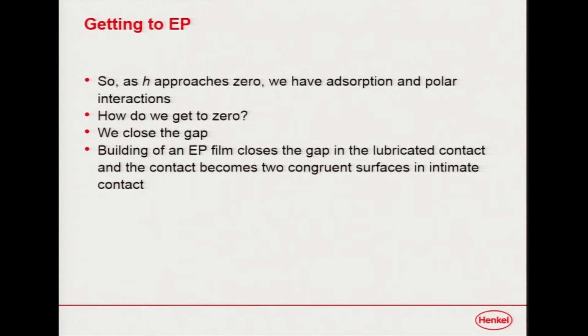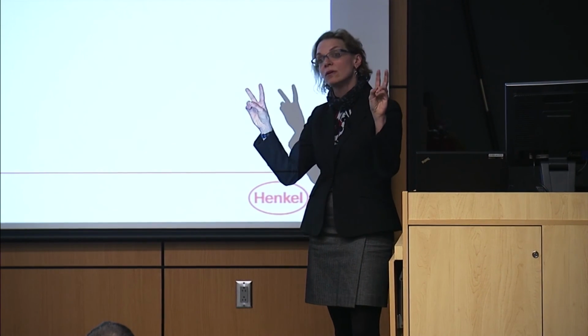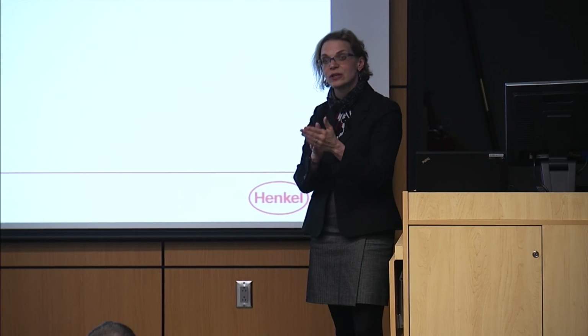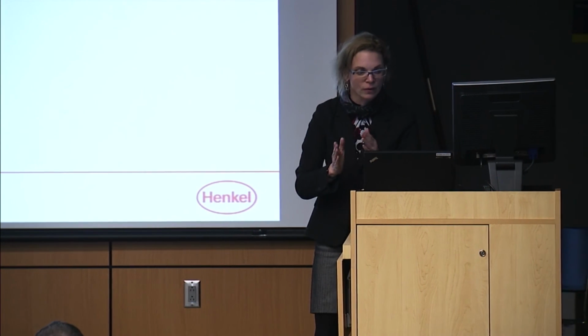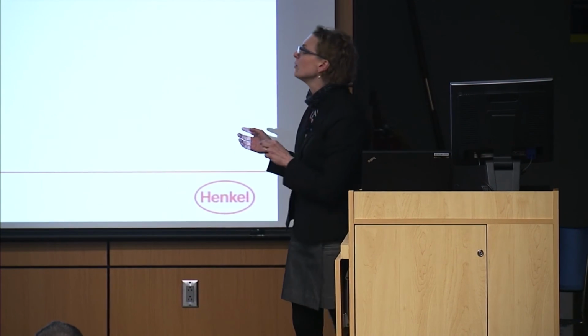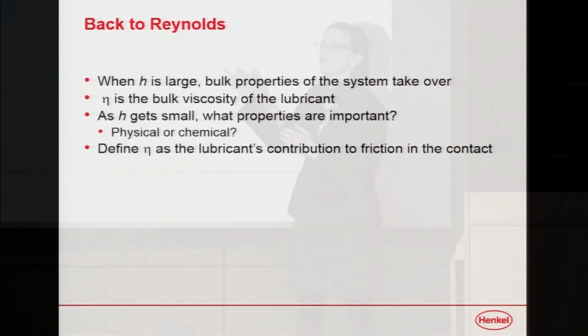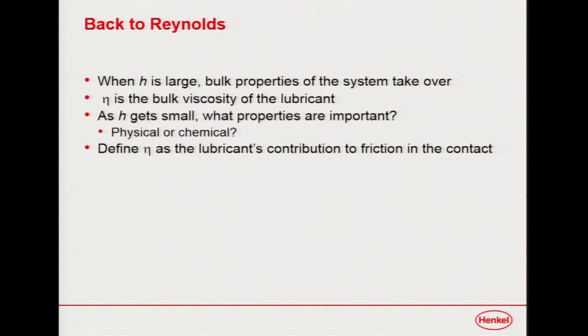How do we get there? Well, we close the gap because we've gotten there. When we build an EP film, when we start to run these reactions, we actually do close that gap. H does come to zero because now you're riding on absolute fully mated films. The surfaces, the actual base metal surface, may still have a shape to it, but it has formed a flowing film in between, and they are now actually completely in intimate contact because of this physical flowing layer between them. It's not a traditional lubricant layer like a Newtonian fluid. It's actually a reacted layer on the surface, which is really, really cool. So we start to go back to Reynolds, and we say when H is large, bulk properties take over. So all you have to know is material properties. Those are your basic paraffins.